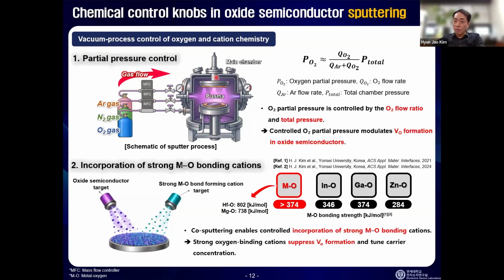How do they make the oxide semiconductor? Conventional vacuum process, sputtering. Okay, sputtering, and then they control the knob, this gas flow, especially oxygen. Partial pressure is the key parameter to decide the property of the thin film.